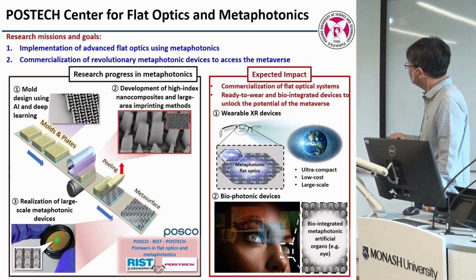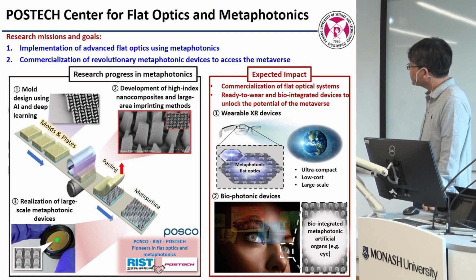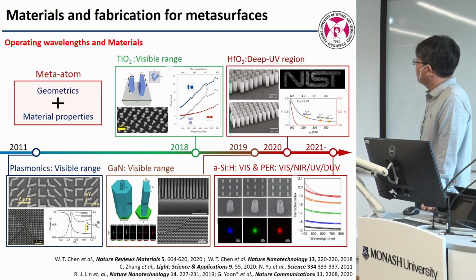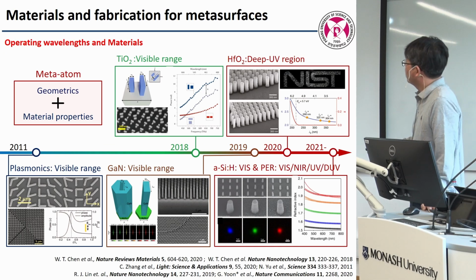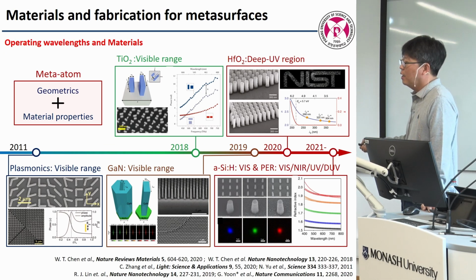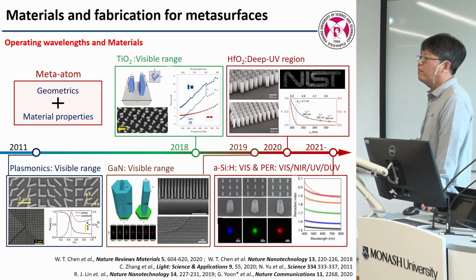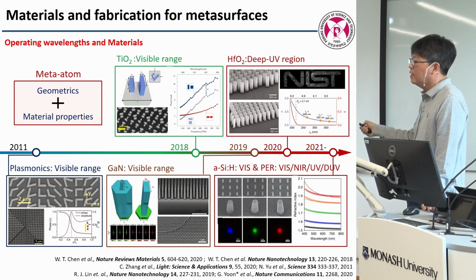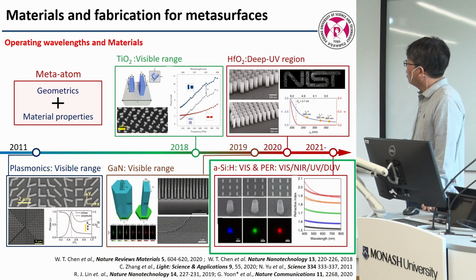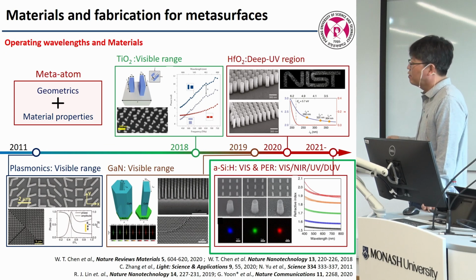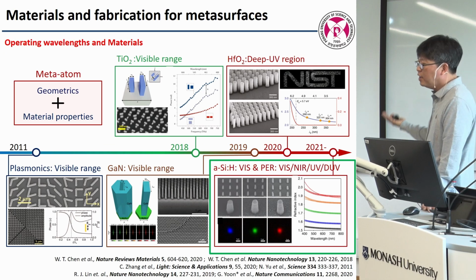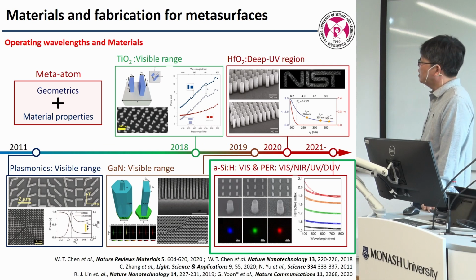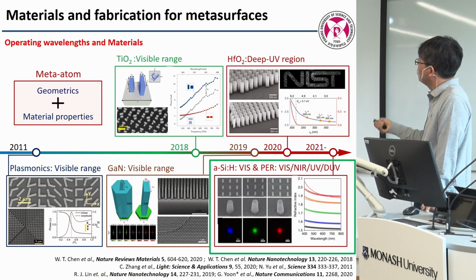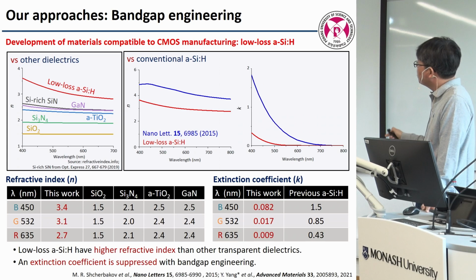But I'll talk about 2 simple things, material and manufacturing. So this is our material development in the community, plasmonics, and then we use dielectric, high and low K. But ALD and MOCVD are beautiful materials, but extremely difficult to do. 1 micrometer of ALD is painful, so not scalable. So what we need is something functionally similar, but can you make it with a cheaper spin coating or CVD? Then we don't need to use TiO2 or gallium nitride, which industry doesn't want to use. So that's our approach, a simple 1 slide.